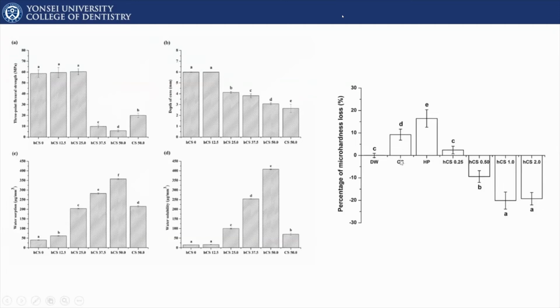demineralization and then expose this demineralized surface with calcium silicate, the percentage of microhardness loss is dramatically reduced, or even a gain of microhardness when we have hydrated calcium silicate. This indicates the hydrated calcium silicate not only neutralizes pH, provides alkaline pH, and provides ion release, but also has an effect in terms of the prevention of demineralization and also remineralization related to these microhardness results.